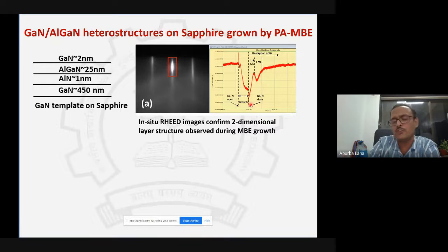So it's giving two things: one is the ordering on the substrate, and the other is the growth of the layer. So you get this disorder and the intensity drops, and then if you stop the shutter or stop the growth, you will see that it regains after some time.